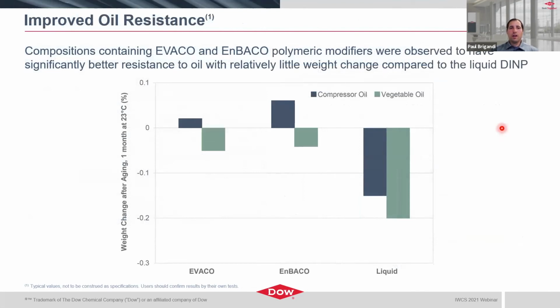So here's another example where we're looking at improved oil resistance. In this case, we've looked at just the two different types of oils, but this becomes important and relevant for us when we start talking about cables that might be exposed to different environments. And you know, there's a host of different fluid resistant tests and encounters where these materials could come into contact with various fluids. But in this case, we're showing just some representative compositions that we showed before, where we're comparing the two polymeric modifiers with that of the liquid.